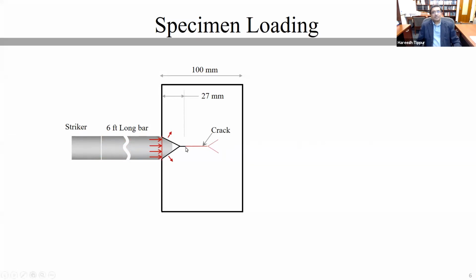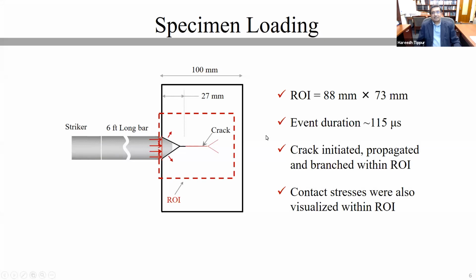Once the crack initiates from the inserted notch tip, it travels some distance and branches without any provocation on its own. The region of interest that we have investigated in this experiment is about 3.5 to 4 inches by about 3 inches. So it is a fairly large area if you consider the sensitivity of the method that I'm going to be showing you later on. The event duration is about 100 plus microseconds, during which the crack initiates, branches, and propagates all the way to the end of the region of interest. We can also measure contact stresses by adjusting the location of the region of interest.